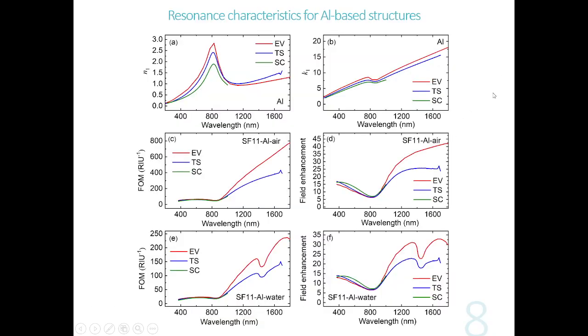Going to the characteristics of aluminum-based structures, they were calculated in the region from visible and a little bit of UV wavelengths up to the near infrared. So we can see that there is an increase in the value of sensitivity and field enhancement at near infrared wavelengths. These enhanced characteristics correspond to the film fabricated by the evaporated method.